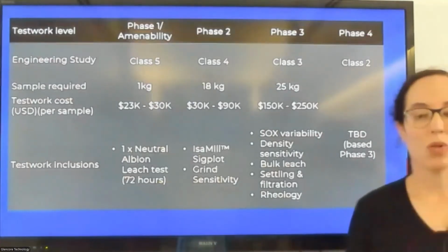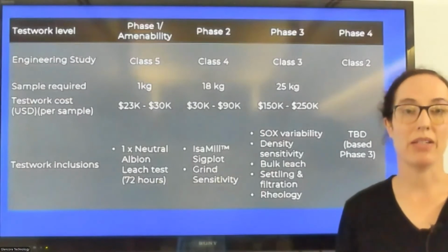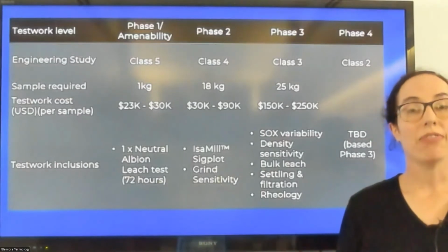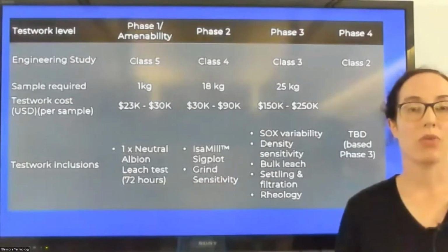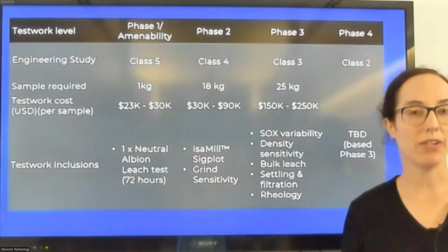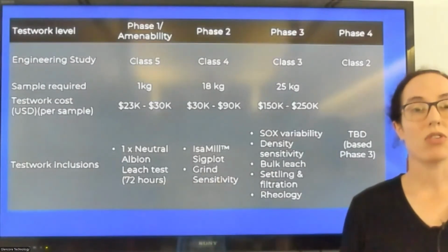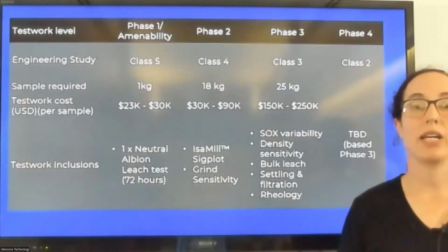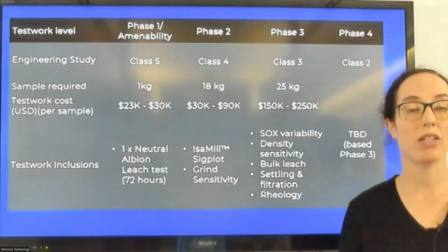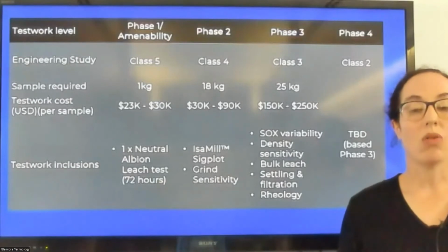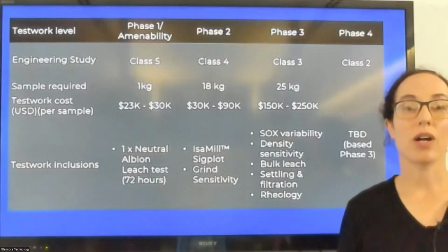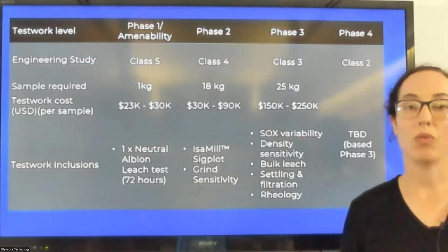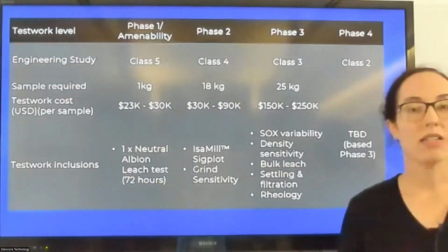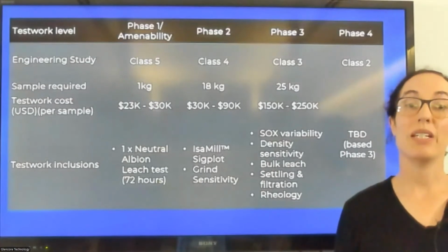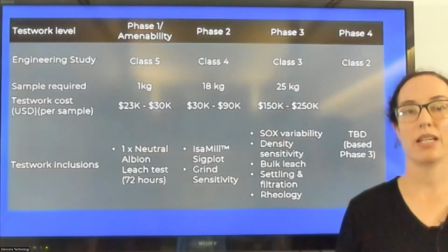Lastly, phase 4 is really very project dependent. If the same sample has been supplied throughout these phases, often you don't need a phase 4. However, if the project has changed, the area you're looking in has changed, or something has changed in the sample, some of the SIG plots, the grind sensitivity, and the SOX variability would need to be repeated, and it will be done here. Ideally, this phase 4 of the test work should be done before the Class 2 engineering study.